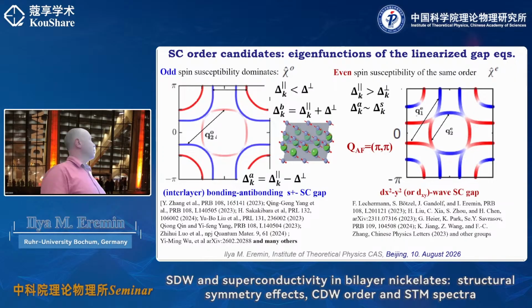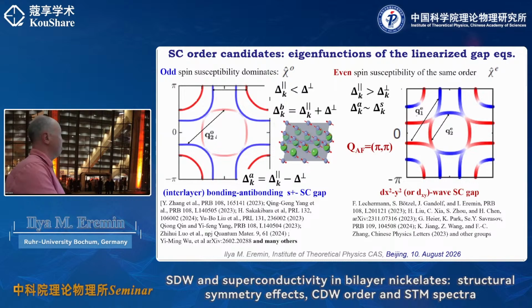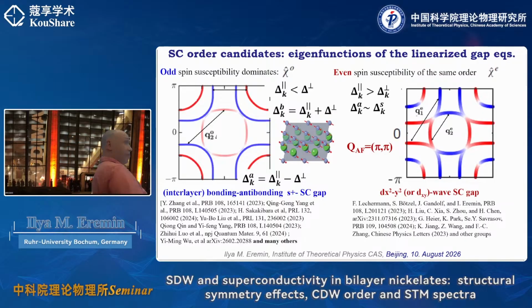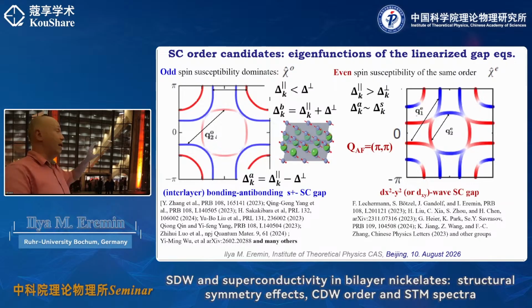So this is how you get this s± order, because if you recollect that these are the bonding bands and this is the anti-bonding band, then the s± tells you that it has to change sign between all bonding and all anti-bonding bands. And that's one of the realizations. And that requires that the delta perp is larger than whatever is in parallel. And it's actually very interesting that if you do an FRG analysis, in this case, the magnetic phase that is seen in the system, there are some details to that, but the instability is indeed connected to this wave vector, which connects basically this pi over 2 in this tetragonal unit cell. It will be a pi over 2 wave vector, and this is the one which also gives rise to the magnetic order. And important is it's also antiferromagnetic between the layers.